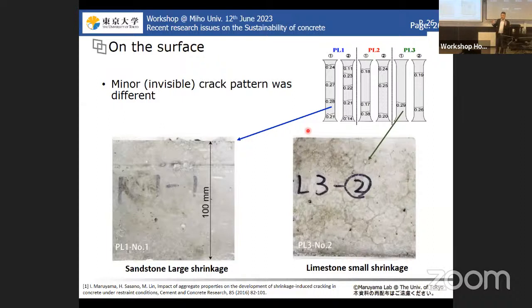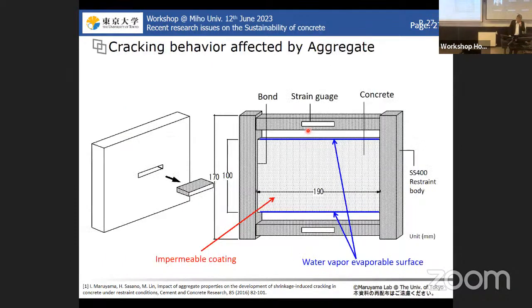So the total shrinkage of hardened cement paste should be comparable, but the aggregate type used is different, and in one type there is a large number of visible cracks, but no fine cracks. But in the case of the limestone, the visible shrinkage cracks are fewer, but a large number of fine cracks was observed on the surface. So to confirm why this happens with the different aggregates, we did this kind of experiment.